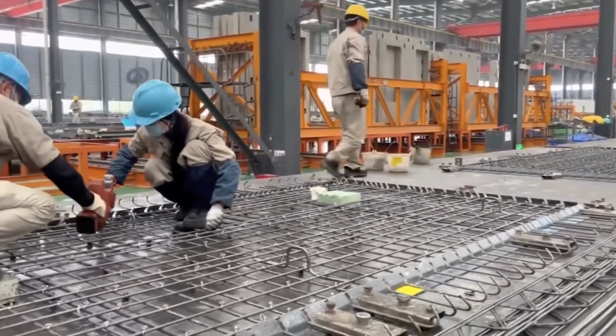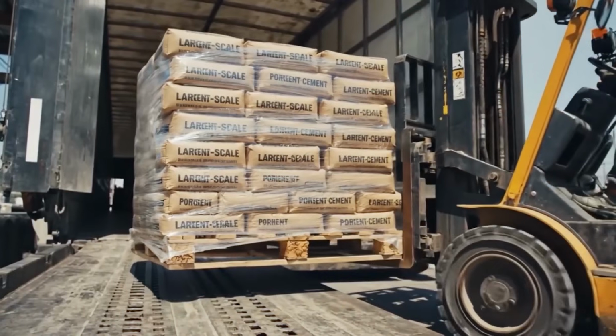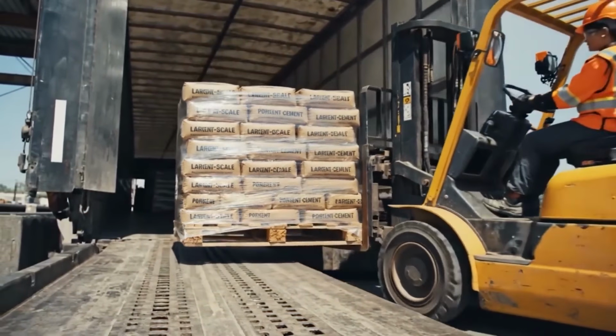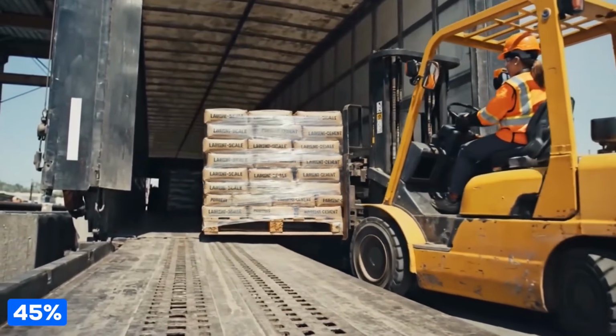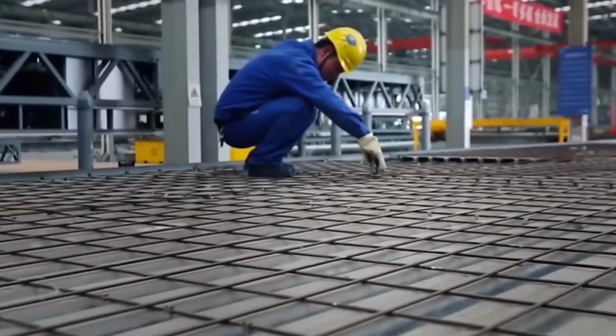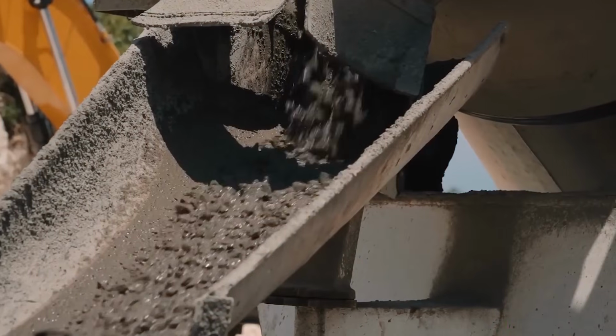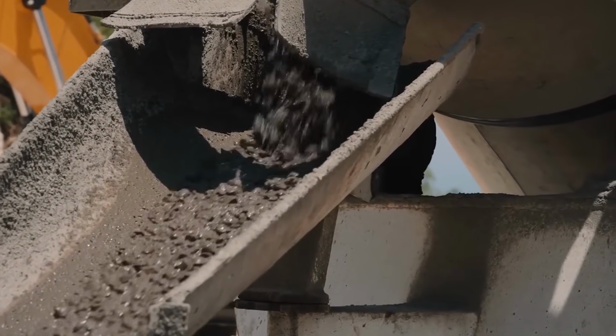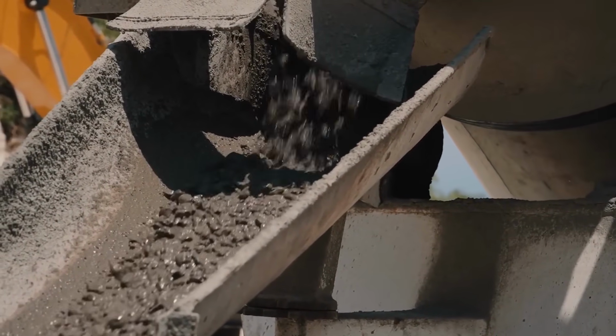Independent testing on this compression cast concrete, or CCC, showed porosity dropping by around 45% compared to standard concrete, and porosity is basically where every concrete failure starts. Cracks form at the voids, water seeps in through the voids, salt and chemicals travel through those same gaps to reach the steel rebar inside and corrode it from within. Less porosity means fewer entry points for basically everything that destroys concrete over time.